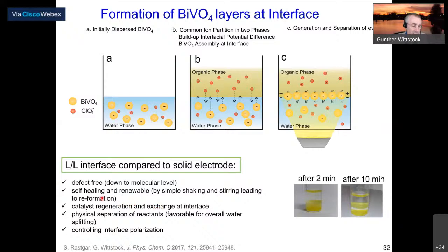So we form a defect-free interface down to the molecular level with self-healing, and it's also renewable. We can regenerate the catalyst in this way, also exchange it. We can use physical separation, which is very established in chemical industry, to handle different solvents. And we can control the interface polarization by the composition of the solution or by an externally applied voltage.